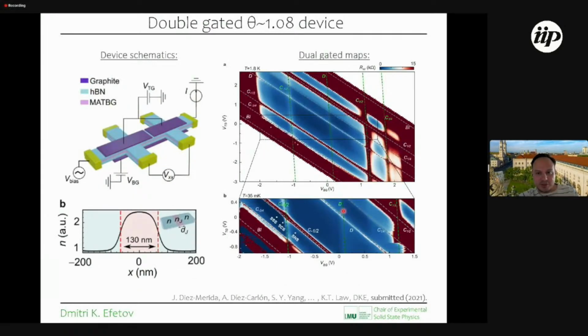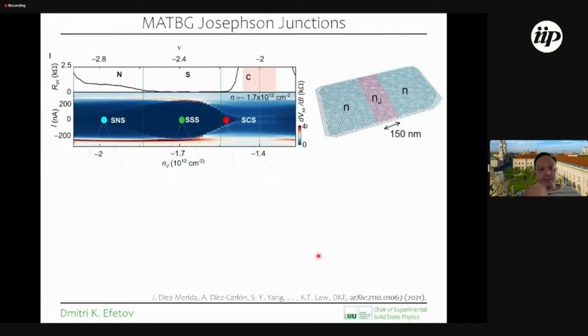And so without going into detail, we create double gated maps like that. By investigating these maps in more detail, we can clearly define regions along which we keep the superconductors fixed, and we really manipulate only the inner region of the device. So this is how the maps look like that we investigate. The color map here shows dV/dI measurements as a function of n_J and as a function of current. And n_J is really the density in the central region. So again, the leads are just superconducting. We change only the density in the central region, and we can do it continuously, sweeping throughout the different phases for the central region. For example, a normal metal region, a superconducting region, and a correlated insulator region at -2.